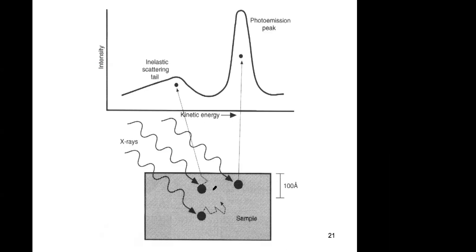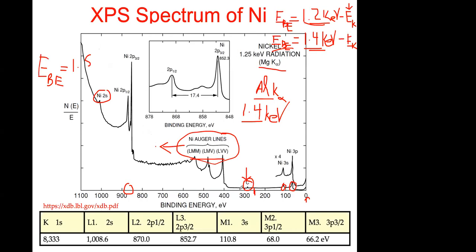I mentioned this yesterday and included this slide. What you see here is sort of the background signal. When you see electrons coming out, you have this increasing background, and the same thing happens here. This increase in background is made of electrons, really Auger electrons, that lost energy because they came from deeper than they are allowed in order to not lose kinetic energy. And this difference you see here is the 2p electrons from nickel that lost energy.